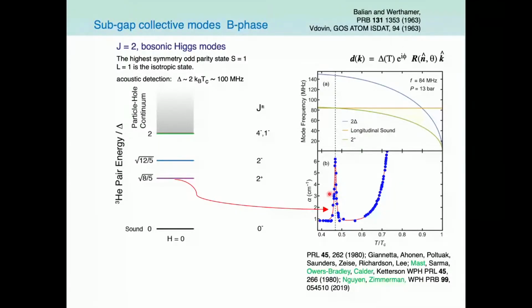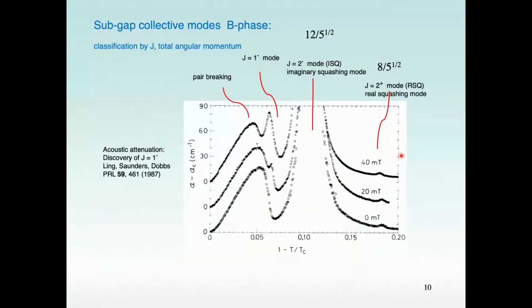And the discovery of this 8/5 state, this subgap state, was made simultaneously at Cornell. And I'd like to specifically mention our chair of session, John Saunders, who participated in this process. And then again, at the same time at Northwestern with my colleagues, students and postdocs shown in green. However, how about this square root of 12/5 state? Well, that you can't see in this scale over here on the right. It's just so strongly coupled to density that the attenuation of sound will not be able to follow this entire mode, this subgap. However, under different conditions, you can see that square root of 12/5 mode, the so-called imaginary squashing